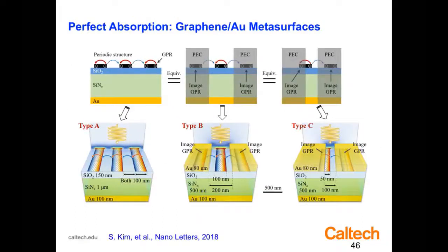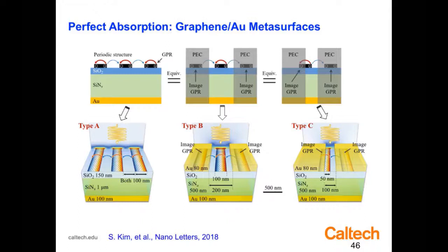But we really wanted to get to 100%. So how do we get to 100%? The way we had to do it was to recognize that the graphene sheets themselves were not conductive enough. We couldn't get the impedance to match the impedance of free space. So we made a more complex structure that had slits in a metal film. And inside each little slit in the metal film, we made ribbons of graphene that were 100 nanometers wide. And the slits in the metal film funnel the light by surface plasmons in the metal into these little gaps. And all of the light incident on the surface gets funneled into interacting with these ribbons. So these ribbons comprise less than 10% of this monolayer on the surface.